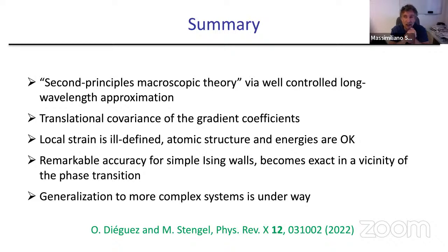In the case of vortices, it's a very good question to know what you need in order to get that out of the polarization. Of course, you need a few more coefficients than what I showed, just because there's not only one component of the polarization. You have also the other component. You probably have strain fields, so you will need to consider electrostriction as well. But I think it's quite feasible if you decide the boundary conditions.